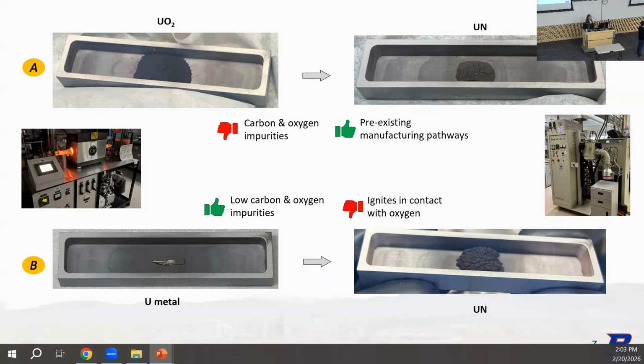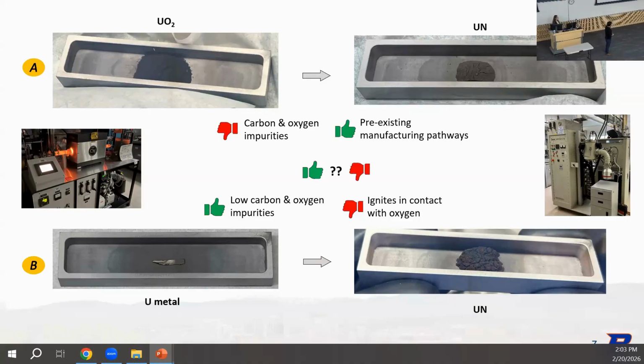However, the other technique, B, gives us low carbon and oxygen impurities, which is very favorable for the properties of the resulting fuel pellets. However, a downside is that the synthesis technique results in very fine powder, which can ignite in contact with oxygen, thus proving an extra hurdle to overcome in terms of the handling and the synthesis. So shifting gears a little bit, there's going to be a variety of things that we find as we go through this process, and we already see some in literature. The list of pros and cons is a lot longer, but it's exciting to be able to dive in and figure out more pros and cons as we continue this work.